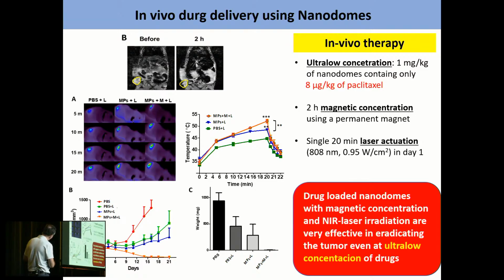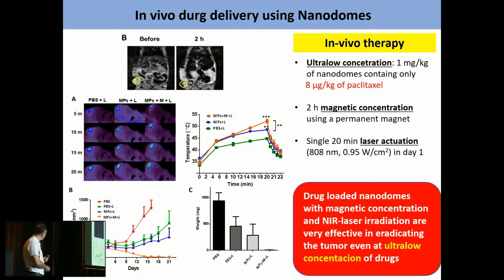When we use the nanoparticles and the laser without concentration, there is a further reduction of the tumor growth. But when we use the magnetic concentration and the laser, you see that after 15 days, we can completely remove the tumors from the mice. So the drug-loaded nanodomes with the magnetic concentration and the near-infrared laser are very effective in eradicating the tumor, even at ultra-low concentrations.